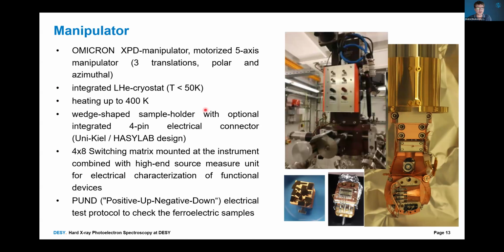And yes, this is our manipulator. It's the good old Omicron XPD manipulator, which has got 5 axes, X, Y, Z, and 2 rotations, polar and azimuthal. It has got a cryostat, also a button heater to heat up the samples up to 400 Kelvin. And also what is special in our design, we have got 4 electrical contacts at the manipulator head, which end up in air, so we can apply bias to up to 4 samples in the manipulator to study ferroelectric samples. Or we can also measure IV curves during or right before the experiments.